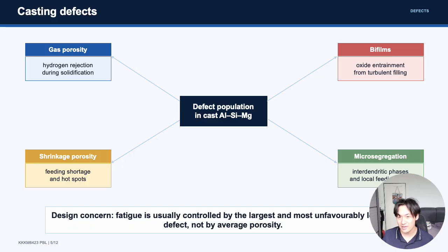The main defects can be grouped into four types. Gas porosity is linked to hydrogen rejection during the solidification. Shrinkage porosity is linked to feeding shortage and hot spots. Oxide films come from the turbulent folding of the outside surface, so they behave more like thin cracks than simple pores. The microsegregation and intermetallic phases can reject solute and create brittle regions. For design, the critical defect matters more than the average porosity.